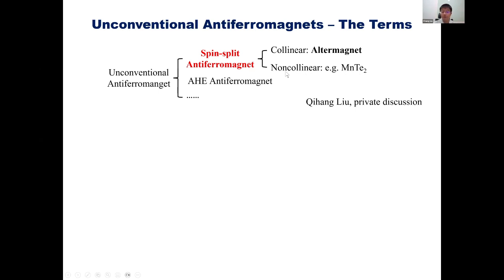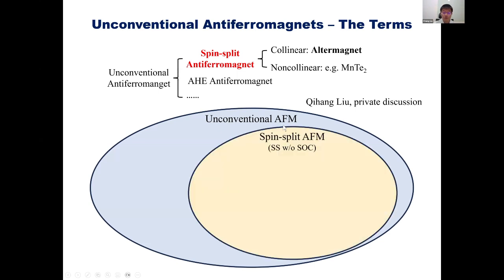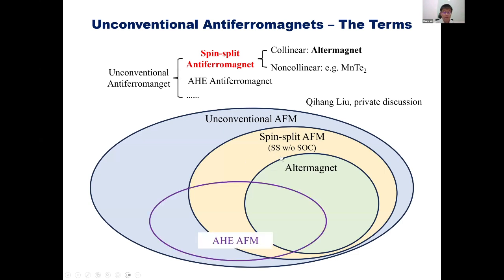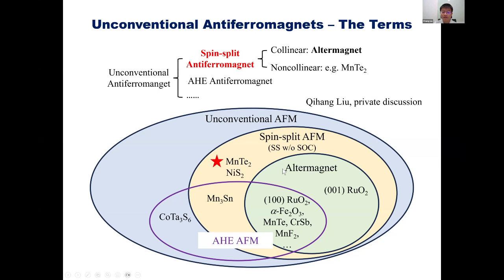Manganese ditelluride belongs to this non-collinear part in this categorization. Both the collinear and non-collinear parts share the same momentum-dependent spin splitting induced by magnetic exchange coupling. On the other hand, the anomalous Hall AFMs are not necessarily Altermagnets, and some of them even have no spin splitting. In other words, spin split AFMs are a subset of unconventional antiferromagnets, and the Altermagnets are a subset of spin split antiferromagnets. While the area of the anomalous Hall effect antiferromagnets spans several regions. The compound we are discussing today, manganese ditelluride, sits here in this graph, meaning that although it is spin split, it is not an Altermagnet by definition. It will have the AFM-induced spin splitting.